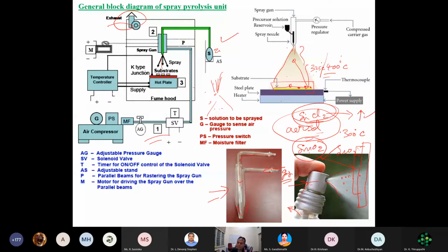Okay, if the cooling is too much, if it goes to 200 degrees centigrade, nothing will happen, because your tin chloride material needs nearly 300 degrees centigrade for decomposition and forming a film. If the temperature is cooled off to 200 degrees centigrade, it will not decompose. So you won't have tin oxide material there. Instead of that, you will simply have tin chloride only sprayed onto the substrate. So this cooling effect has to be taken care of.